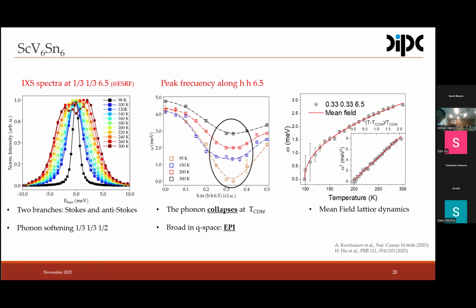It's a soft mode that freezes down to a long range charge density wave with long range charge order. And on the other hand, the fact that this softening is broad in momentum space indirectly tells us that we are mostly dealing with a momentum-dependent electron-phonon interaction and not with nesting. We can further track the temperature dependence of the soft mode, and again, we see how it follows a mean-field behavior with very linear temperature dependence from room temperature down to the charge order transition.